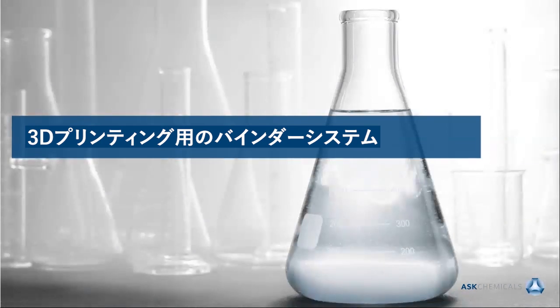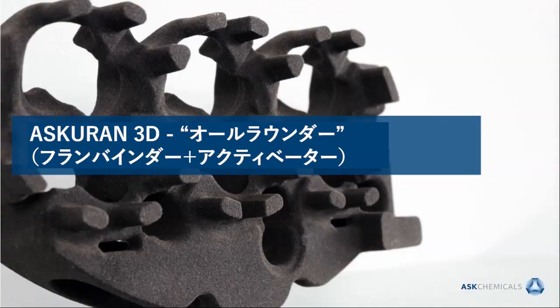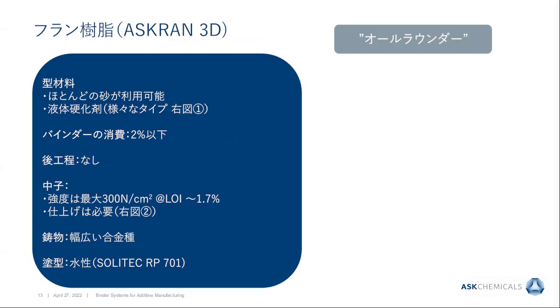So let's have a more detailed look into the printing systems provided by ASK. And let's start with ASKURAN 3D, which is a furane binding system combined with a liquid activator in the sand. So in terms of the molding mixture, most sand types are applicable with this system. And as already mentioned, there is a liquid hardener which can vary in type, and the variation in type already gives one the possibility to steer the process in terms of reactivity.